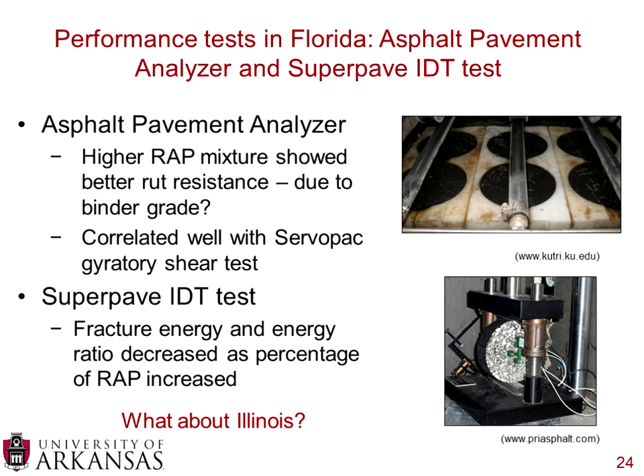Because one could argue that by dropping down from a 67 minus 22 down to a 58 minus 28, that drop of binder grade did not completely account for the additional stiffness that the wrap put in there. So I think there are two confounding factors. One, you're changing the wrap content, and two, you're changing the binder grade, and I don't think anyone has yet been able to completely decouple that. So, Riyadh, to answer your question, I don't think we know whether the binder grade or the wrap is what's really influencing the rutting resistance or even cracking resistance, and I think that's something that we're going to have to continue to investigate as time moves on.